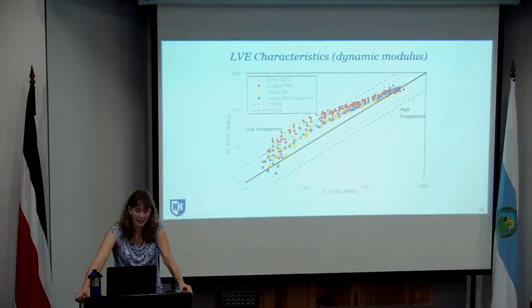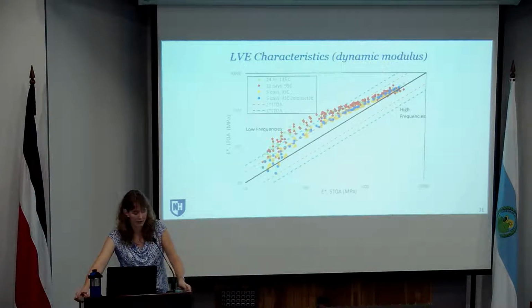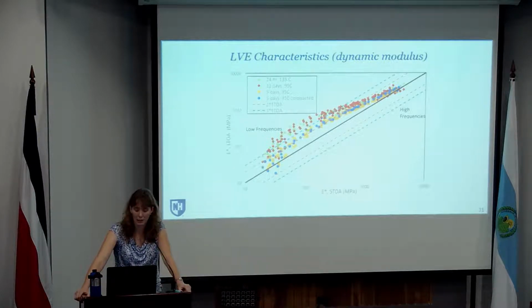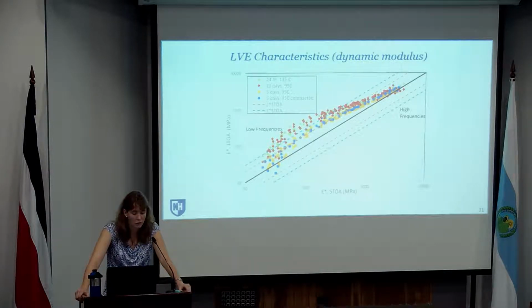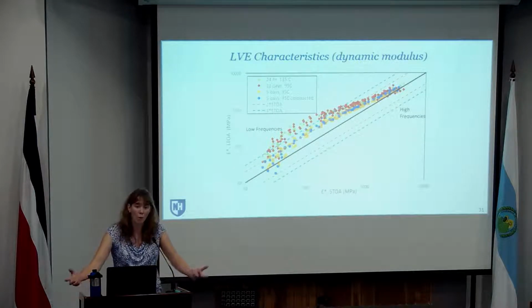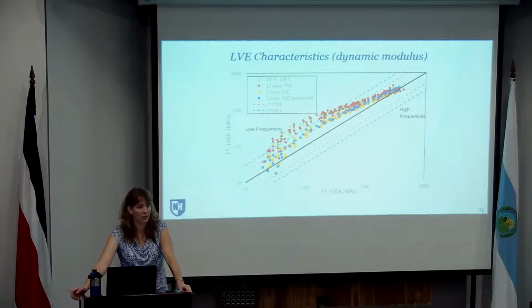So you can see at the low frequencies and at the high frequencies, okay, so the low frequencies are on the lower left, high frequency on the upper right, there's not as much impact of the aging conditions, the longer term aging protocols, in terms of changing the stiffness. When you get into those mid-range frequencies, you can see changes in stiffness of 2, 3, or 4 or more times in terms of the change in the stiffness.